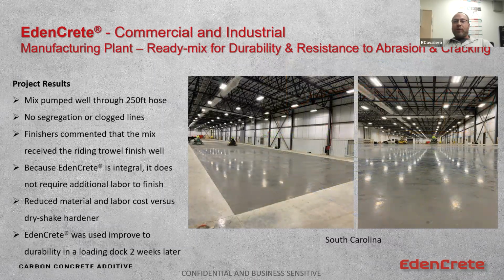When they get done, they're able to bring the cream up to the surface fast enough that they don't have to burn it. So when they're tasked with a burnished finish, like your garage, you often see it's black or dark gray. They're able to get the cream up fast enough with EdenCrete that they can get this almost marbled look, because they can do it before it burns it. And in an interior lighted application, it really takes on a cool effect across the large scale.